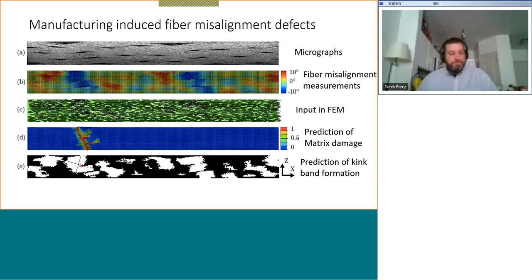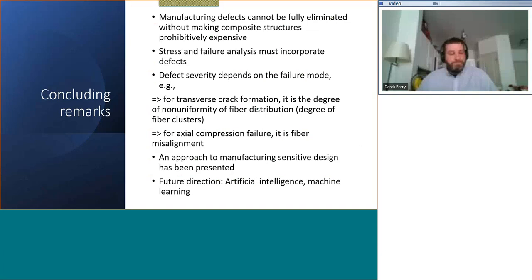Yeah, I'm not going to go into detail, but tell you that there's an integrated methodology that starts with observations of micrographs, digitizes them, and puts them in a finite element model, and then using physical modeling that I talked about, predicts where failure will initiate. This particular example is for fiber waviness, where the composite structure is mostly loaded with compressive loading, because that is a very severe situation compared to tension many a times, because with fiber waviness you start out kink bands and failure of fibers and delamination between layers if there's a thick composite, as I was talking about. So at the last image you see in the bottom, there's a comparison of predictions with actual observations. So next slide is going to conclude. Next, please.